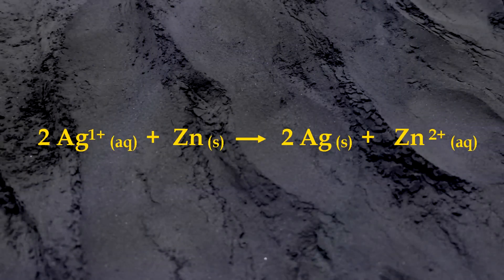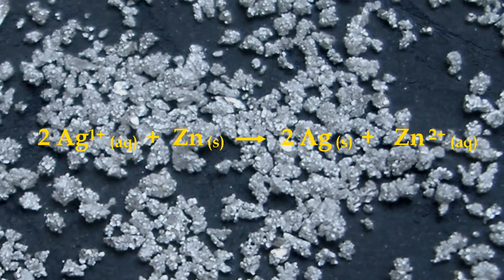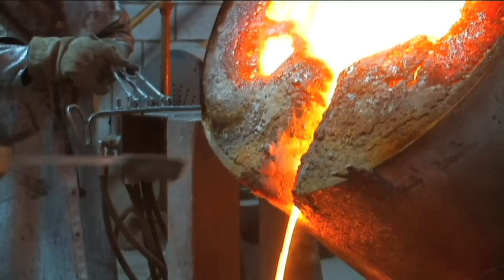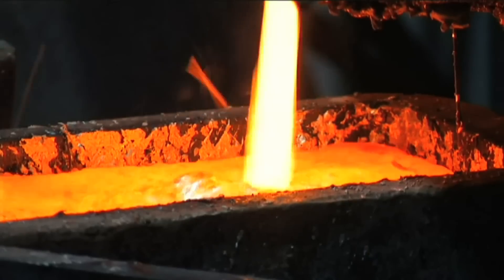Dissolved silver is precipitated or cemented out of solution in a concentrated form with zinc dust, for example. It is then filtered, dried, and melted into dore bars for further refining.